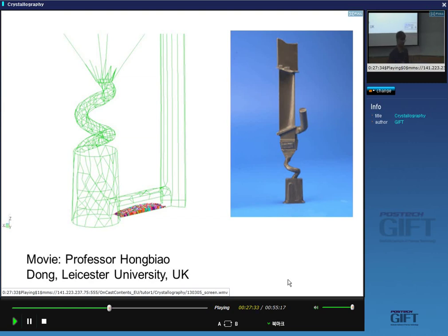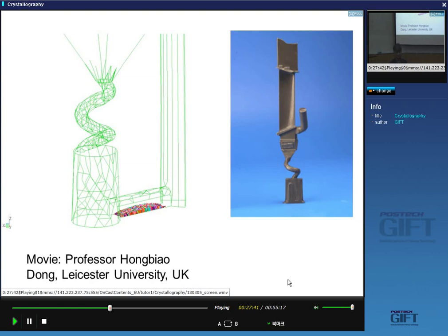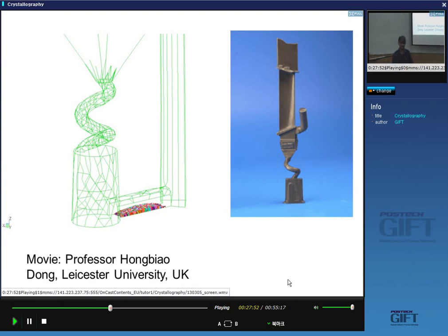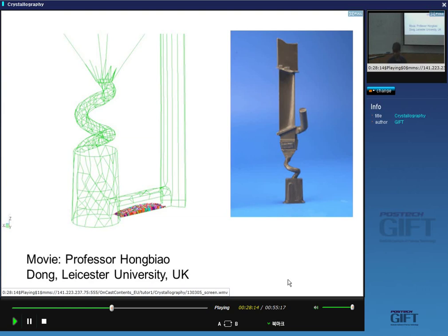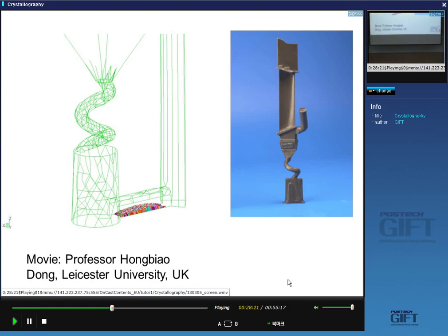No reasonable material can operate unprotected at 1400°C under those stresses. Two things are done: a ceramic coating acts as an insulator creating a large temperature gradient across it, and cooling air at about 600°C is passed through the blade. The total blade is maintained at about 1000°C. The wall thickness is very thin — on the order of one and a half millimeters — yet there are really complex cooling channels going through it.